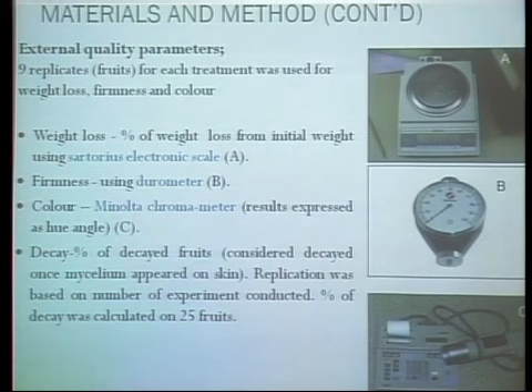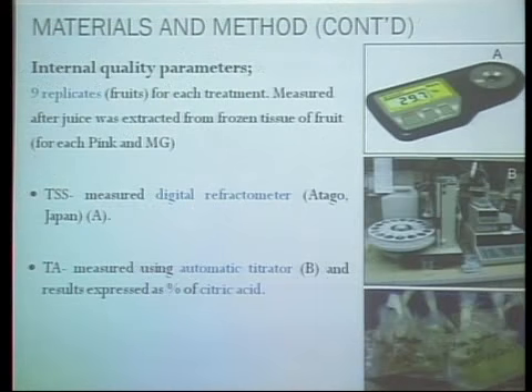And then the decay, we considered a fruit as decayed when we saw a mycelium, that is after we had taken them from storage. For the decay, the replication was based on the number of experiments. But for each treatment, we calculated the percentage decay out of the 25 fruits. Okay, so we have the internal qualities. For the internal qualities, we have 9 replicates, as with the external. For TSS, we had 9 replications. The TA also, we have 9 replications. The TSS was measured using the digital refractometer, as you can see. And then the TA was measured using the automatic titrator, and the TA was expressed as the percentage of citric acid.